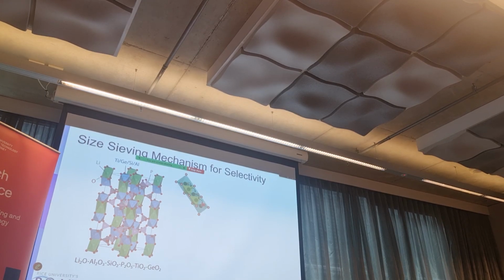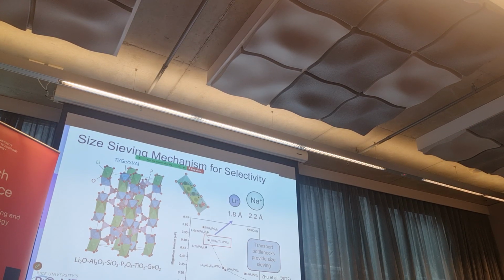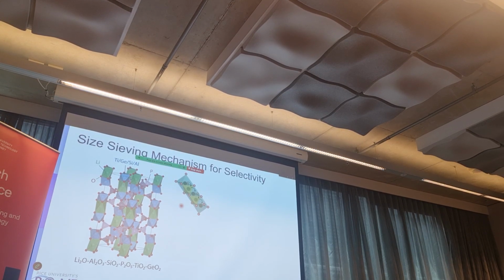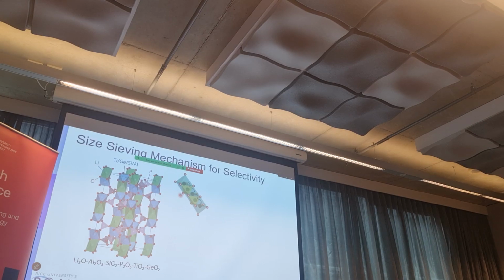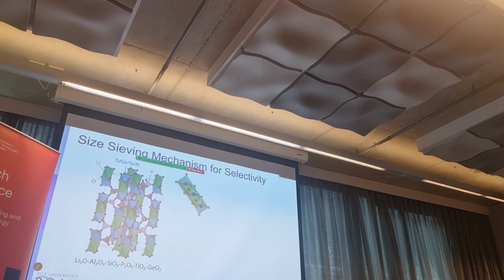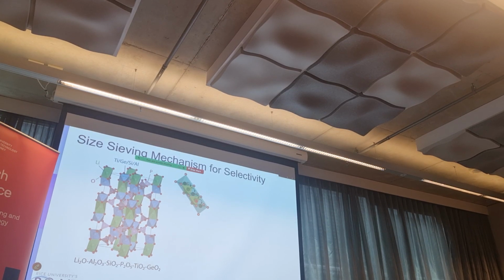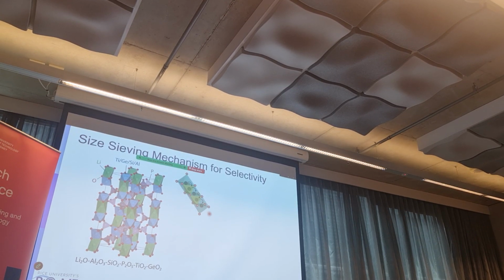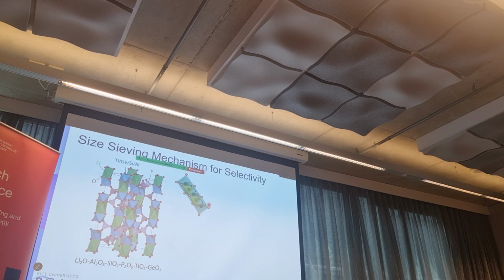Now here we have a size sieving mechanism. Before going over that, let's look at the mechanisms of lithium transport in a solid state electrolyte. There are two: one is by vacancy, where if you have some vacant sites, lithium will go from one vacant site to another, well known from solid state diffusion and battery research. Also, you can have interstitial transport, through the interstitials between the polyhedra.